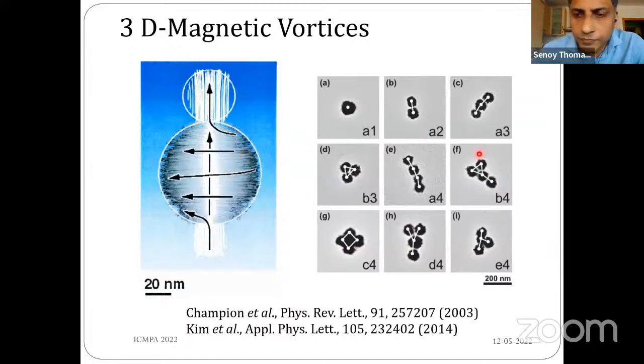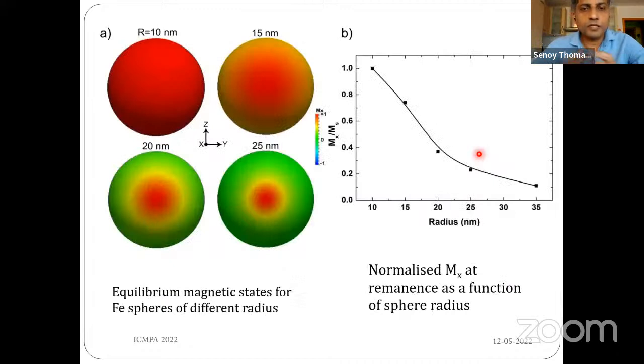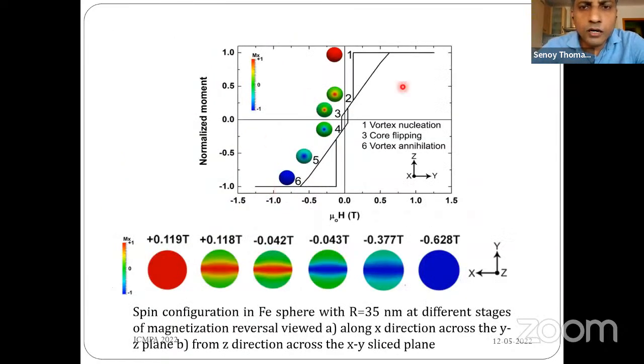soft ferromagnets. So we also performed micromagnetic simulations on iron spheres having different radius ranging from 10 nanometer to 25 nanometer. What we found is that at a very small size, the system is in a uniform state, and if you increase the diameter, then there is a good possibility for nucleating a magnetic vortex spin configuration in these spherical nanoparticles.